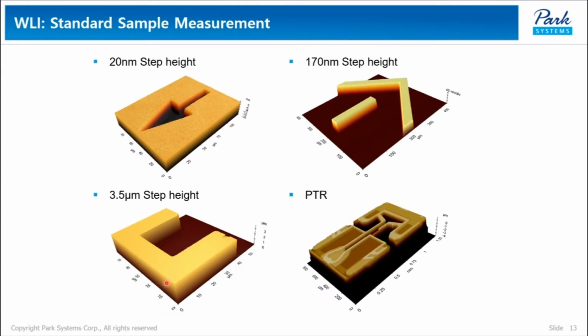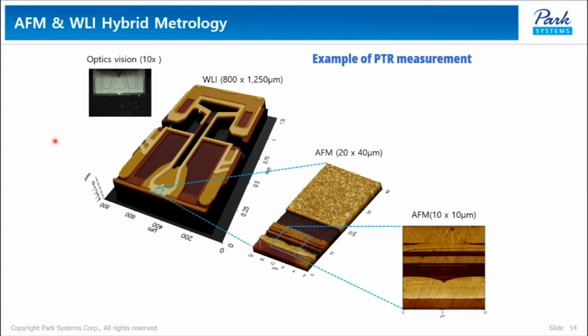WLI has a strength in measuring higher sample height from a few hundred nanometers to the micrometer range. These are WLI images of a standard sample and a hard disk drive. This is an example of the WLI and AFM imaging process in sequence. From optical view, WLI is able to provide a large 3D view of the sample, which is 800 micrometers by 1250 micrometers. Then AFM zooms in to locate very small target objects such as a pole tip recession, which reads and writes in a hard disk drive.